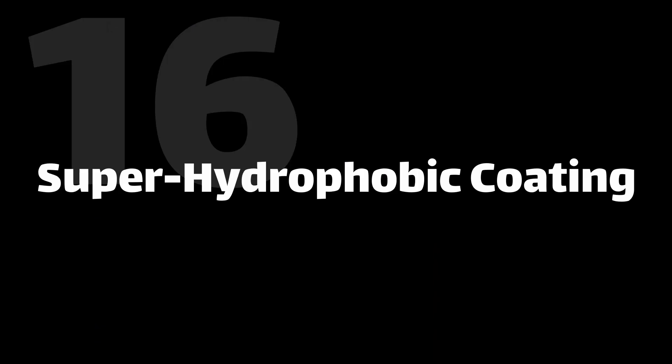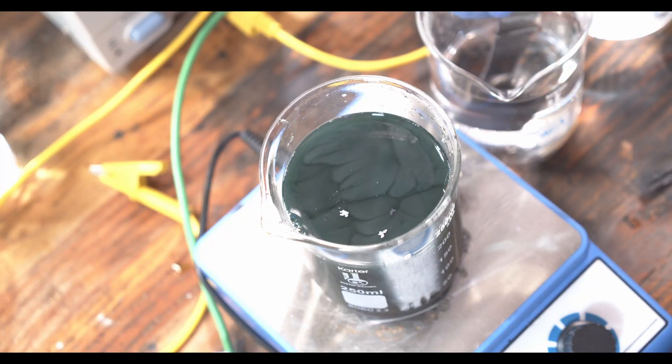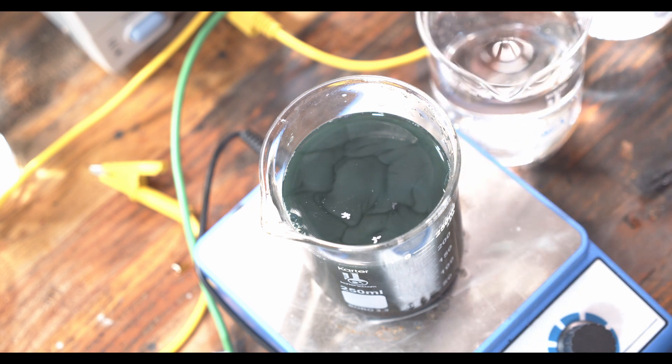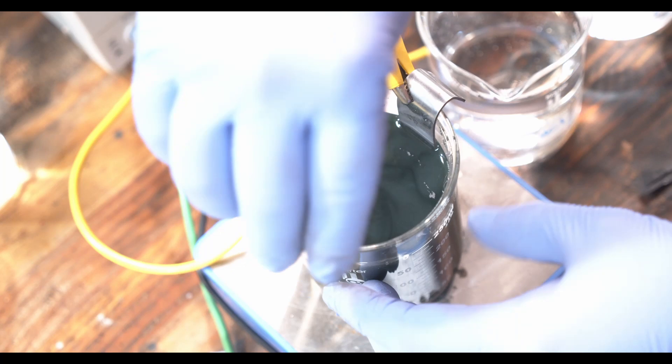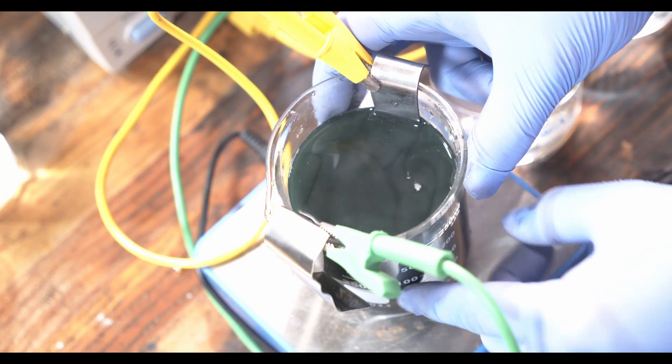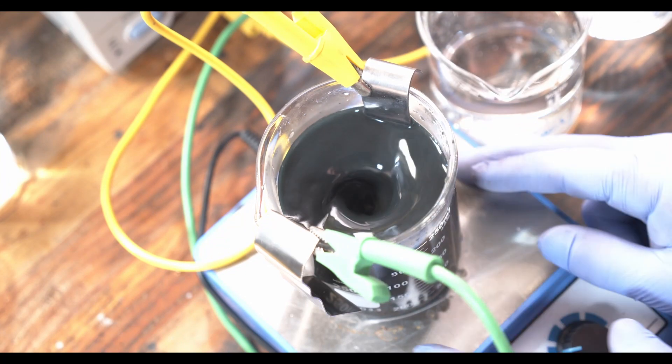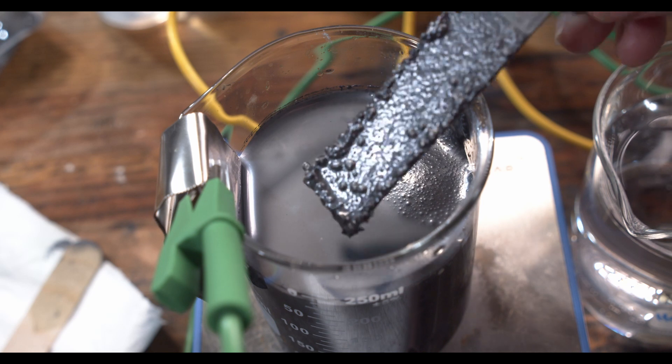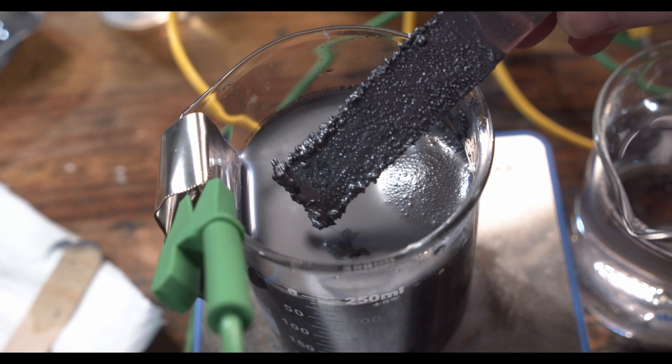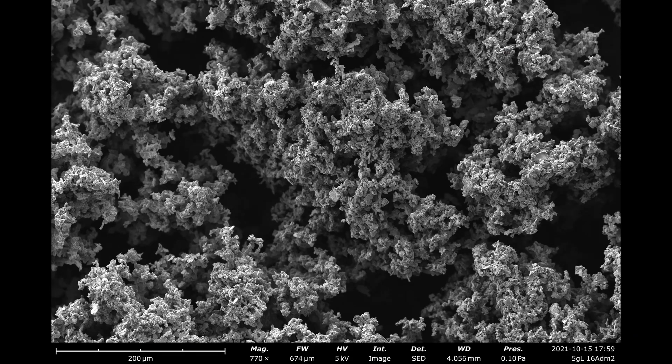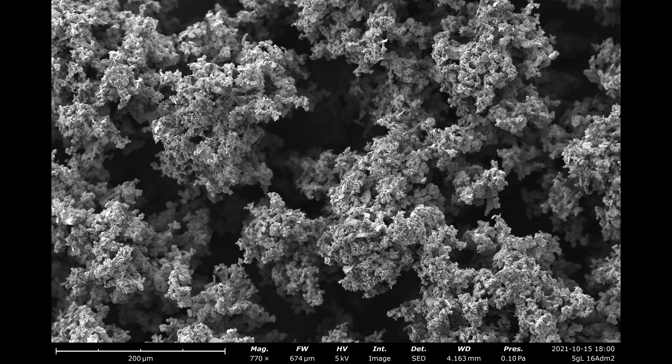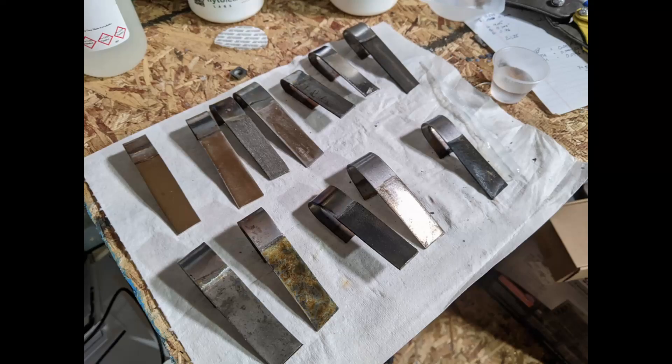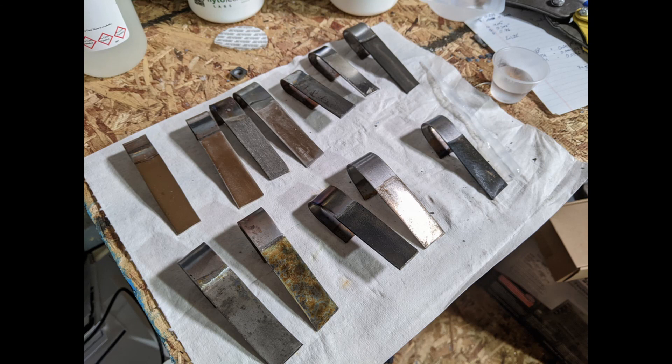This was a silly project where I was trying to replicate a paper that generated a super hydrophobic coating - a coating that doesn't like water. This was another one of those papers with a deceptively simple protocol. You add an inert and very low surface energy additive into an electroplating solution. For the paper they used nickel as the electroplated metal and tungsten disulfide or teflon which is added in. The inert substance itself doesn't electroplate but it'll be incorporated into the nickel as it plates out just by accident. If everything goes right you get a surface that has very low surface energy and high roughness which doesn't like water.